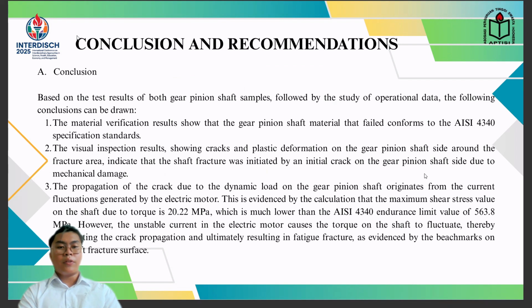One, the material verification result shows that the gear pinion shaft material conforms to the AISI 4340 specification standard. And two, visual inspection results show cracks and plastic deformation on the gear pinion shaft around the fracture area, indicating that the shaft fracture was initiated by an initial crack on the gear pinion shaft side due to mechanical damage. The propagation of the crack due to dynamic load on the gear pinion shaft originates from the current fluctuations generated by the electric motor.